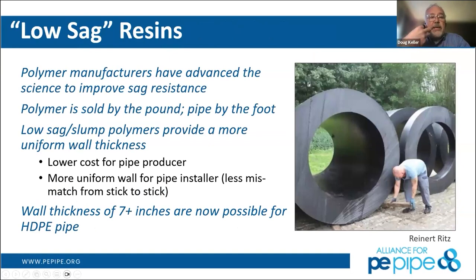So what we've been able to do is, again, address an issue with the industry, which was a maximum wall size that was possible. And we'll show a chart later on from F714 that shows where beyond a certain dimension ratio sizes weren't available. We're now able to have a material that resists movement while in the molten phase to allow for a more uniform wall thickness. The importance here is that a pipe producer is buying polymer by the pound, but they're selling it by the foot. So the less material that they can put in, the more economical the pipe is to be sold. And for an installer of the pipe, it means that you have less variation in wall thickness.